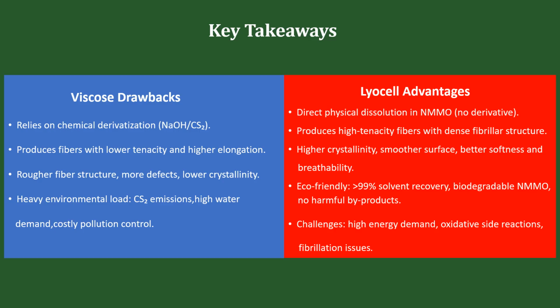From a sustainability perspective, lyocell offers a major advantage through closed-loop solvent recovery exceeding 99% and the absence of harmful sulfur byproducts. Although challenges such as energy demand and fibrillation remain, lyocell is widely recognized as the more sustainable and high-performance cellulosic fiber technology.